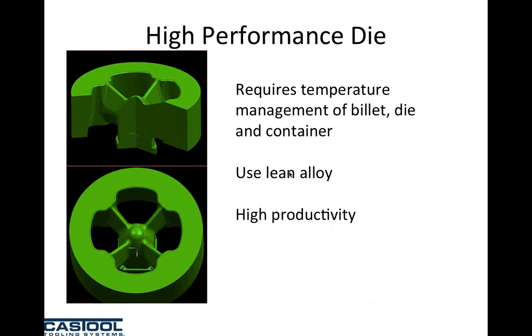A lot of extruders say, great, I want one of those high-performance dies. But unless your billet temperature is plus or minus 10F, your die temperature is plus or minus 10F, and your container is stable at plus or minus 10 degrees Fahrenheit, unfortunately, it won't work. Your die corrector will come back to you and say, look, we tried that die, we got lousy profiles out of it, give me a thick die with long bearing so I can fix your problem.